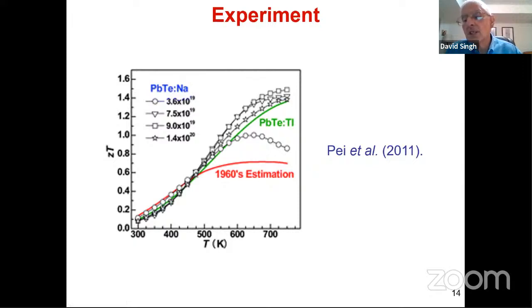I mean, it wasn't just because they were lazy, it was because there were issues with the phase diagram that had to be overcome in order to do this. So it was not a scientifically easy thing to do. But anyway, if you just had the right amount of sodium optimized according to the band structure, then you didn't need this poisonous element thallium to change the band structure, but you could achieve this with sodium, and then you could achieve a much higher efficiency. And so lead telluride, in fact, even though it was industrial, was not optimized in the 1960s. An amazing fact, I thought.